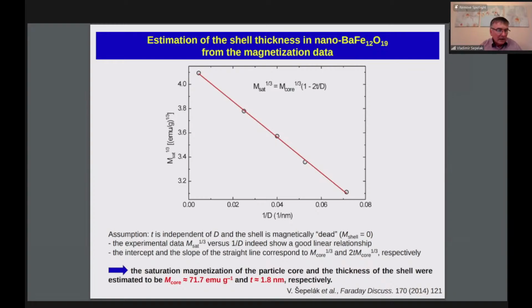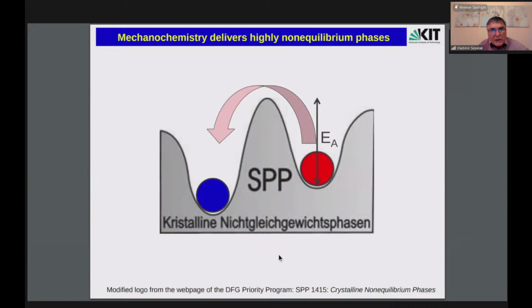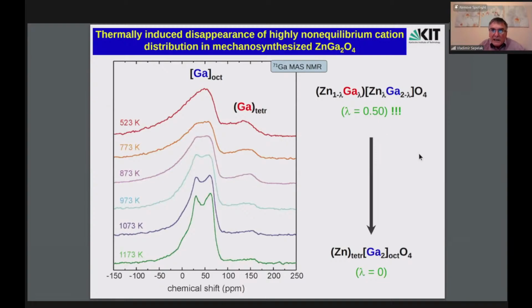And very shortly, I would like to mention that all these materials are highly metastable, and I will show only 3-5 examples on the thermally induced disappearance of the highly non-equilibrium cation distribution in mechanosynthesized, in this case, zinc gallate. You see gallium-71 magic angle spinning NMR spectra. For mechanosynthesized material, we observe again 2 subspectra corresponding to occupation of gallium on octa sites and tetra sites, and